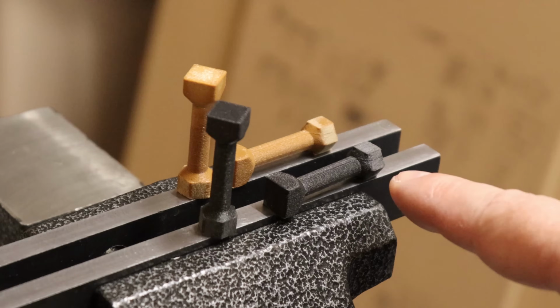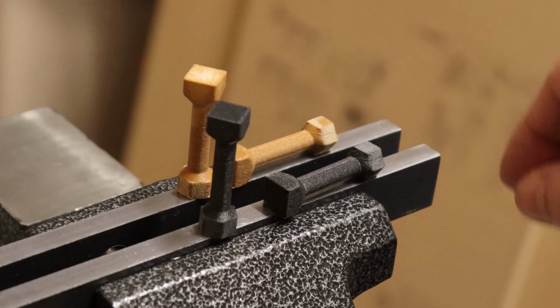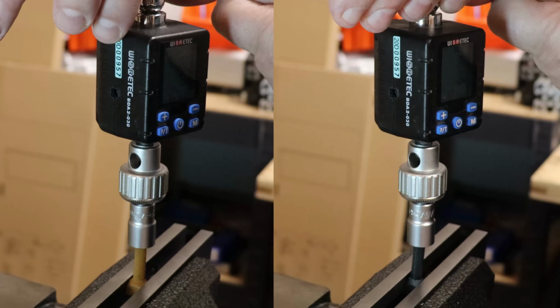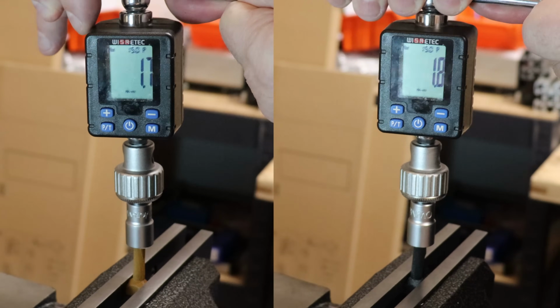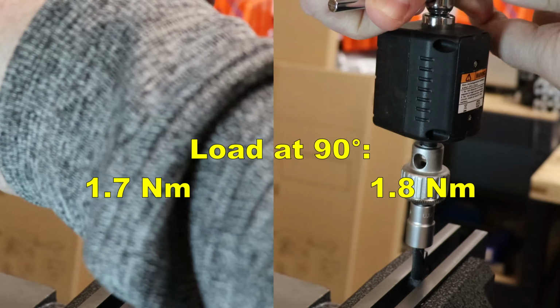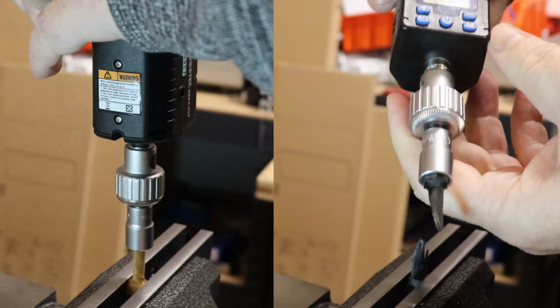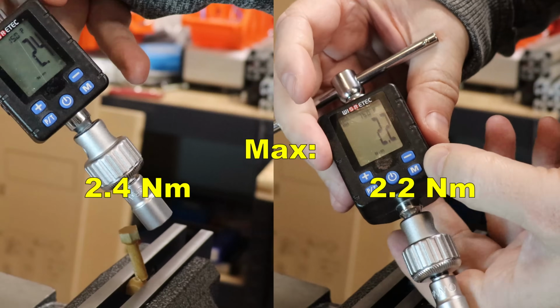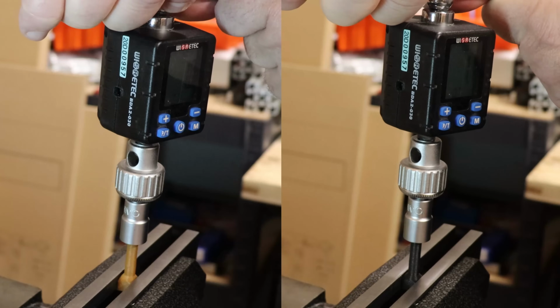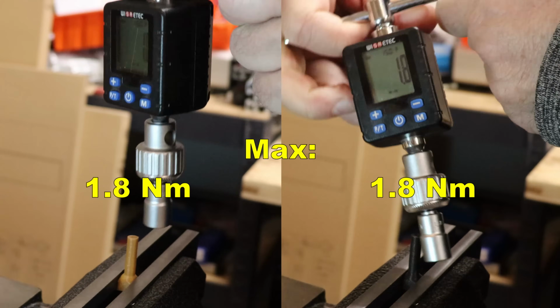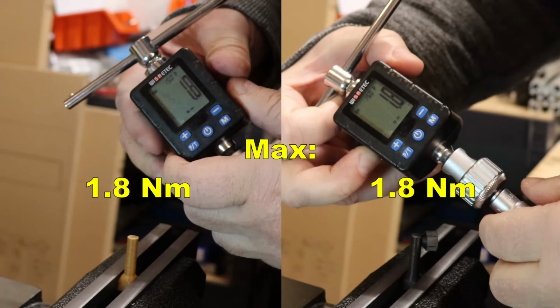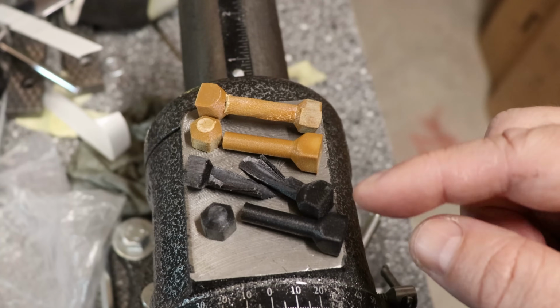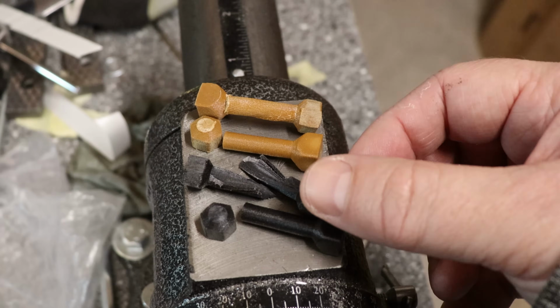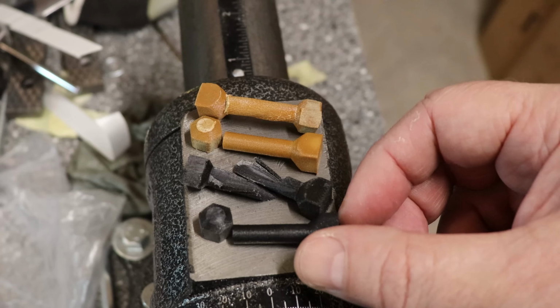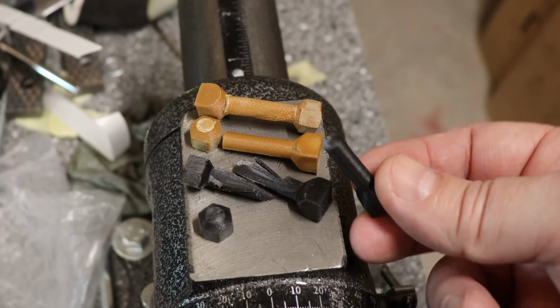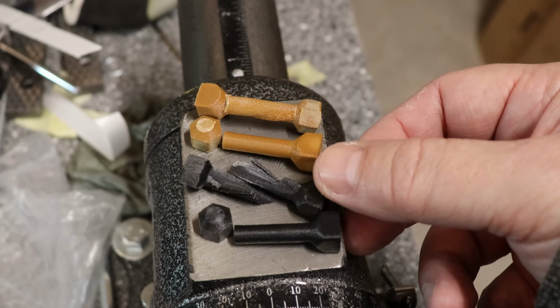Torque or twist test with horizontally and vertically printed test objects, and I'm starting with horizontal ones. And I'm recording the load at a 90 degree rotation. And the maximal break load in Newton meters. And these are printed in vertical position. Similar load but breaks more suddenly. Interesting to see that the carbon fiber version breaks more suddenly, even this printed horizontally, but of course the break type is different, until the vertically printed breaks along the layer, until this horizontally printed have this type of the break.